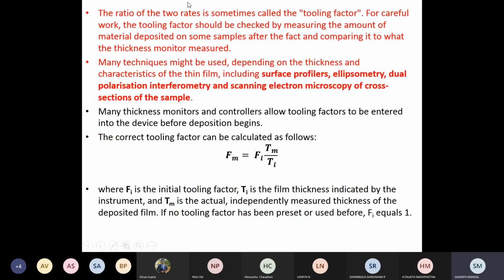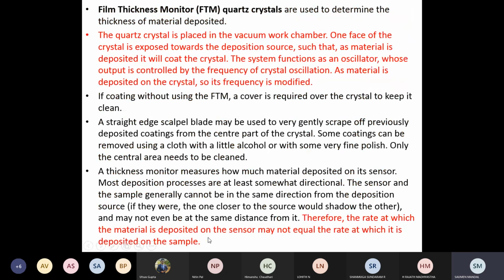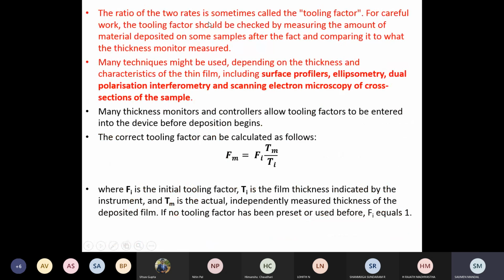The ratio of the two rates is sometimes called the tooling factor. So what is the ratio of these two? The rate deposited on the sensor and that deposited on the sample. This ratio is called the tooling factor. For careful work, the tooling factor should be checked by measuring the amount of material deposited on some sample after the fact and comparing it with what the film thickness monitor measures. So the tooling factor is very important. In fact, you need to monitor the tooling factor on a regular basis.